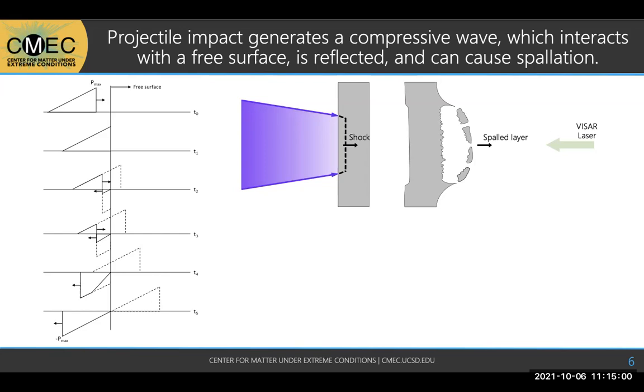And so eventually you can see how that incoming and that reflected wave start interacting until you get this completely negative, or tensile, wave. And that tensile wave is the cause of spall. If those stresses were large enough, you actually tear the material apart. So that's what I'm showing in the simplified drawing. It's that spall scab flying off the back. And then VISAR, which is generally what we use for laser shock experiments, is what we use to measure the velocity of that back surface.